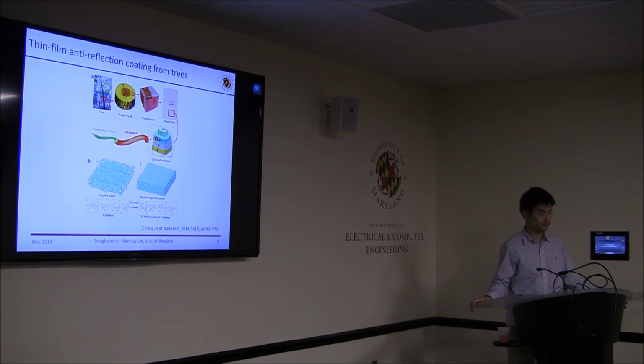Okay, let me go back to the previous slide. This schematic and these pictures are from a previous paper of mine, from Nano Letters. To make these papers, first we needed to change the concentration of the cellulose fibers. We can adjust the concentration by changing the fraction of the water and the cellulose fibers. If we pick a proper thickness and length of the cellulose fibers within a solution, the paper making technique is very simple. It was originally in solution, and we can simply dry it, and we can achieve the cellulose fibers.